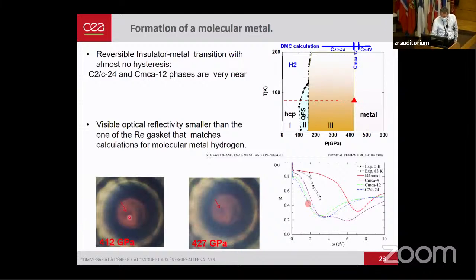And this is a sample before the transition. You can see it's black, and this is the rhenium gasket. The gasket should be metal, but since the diamonds are under extreme pressure at 412 GPa, the diamonds start to look a bit red. And after the transition, it is still black. There has been some calculation that if you have an atomic metal hydrogen, it should be highly reflective. If you have a molecular metal hydrogen, it should be less reflective, 0.4. So it's compatible with this calculation.